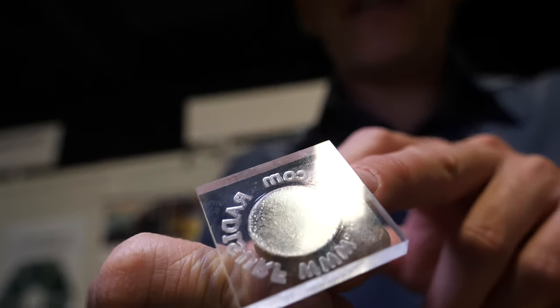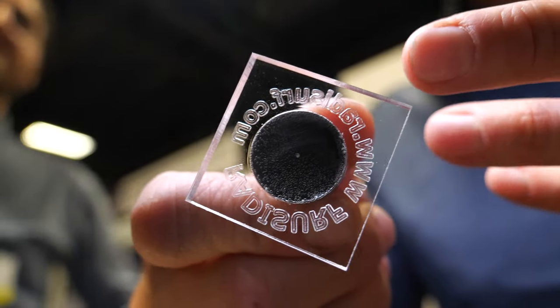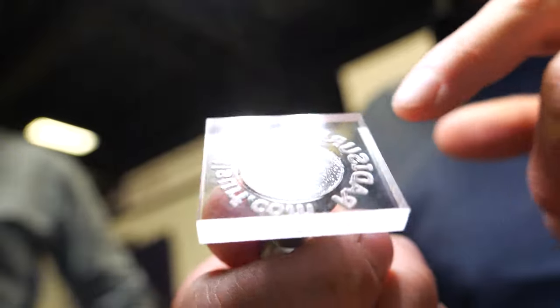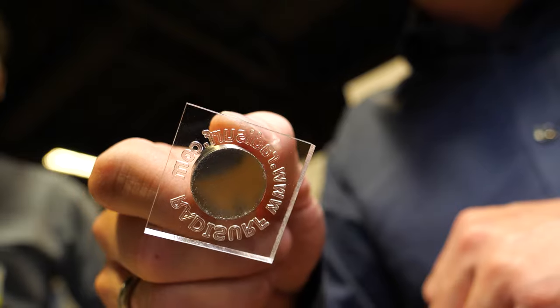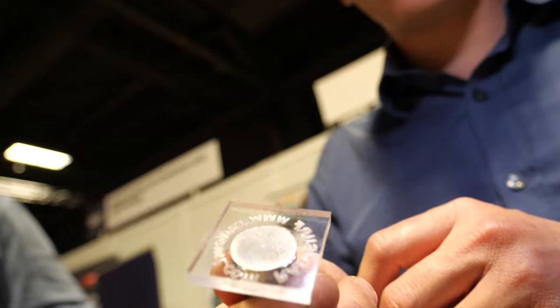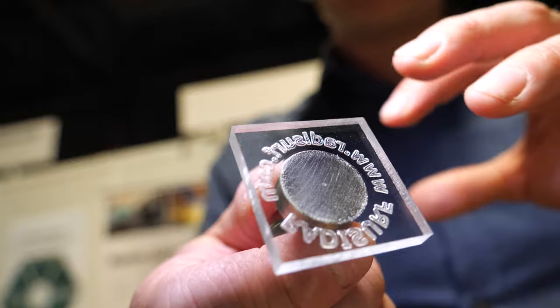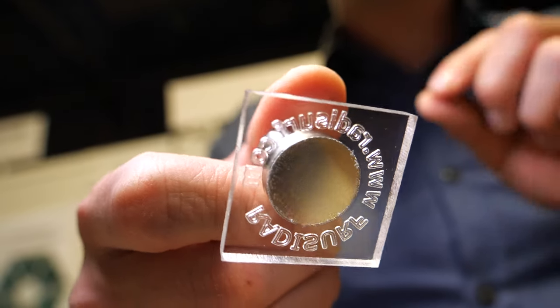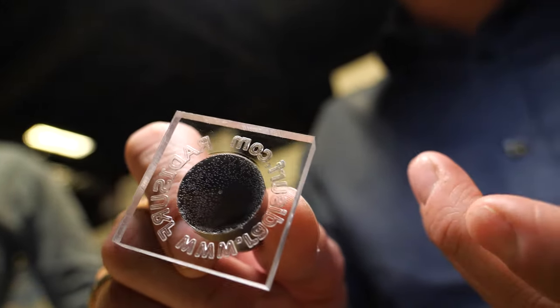What we essentially done here is to make a 50 nanometer thin organic coating on the stainless steel part and then we welded the acrylic onto it to get a really strong and tight bonding between the materials. In between there's only a 15 nanometer thin layer of what we call polymer brushes — plastic strands that are chemically bonded to the metal part and entangle into the plastic part, creating a direct chemical bond between the metal and the plastic material.